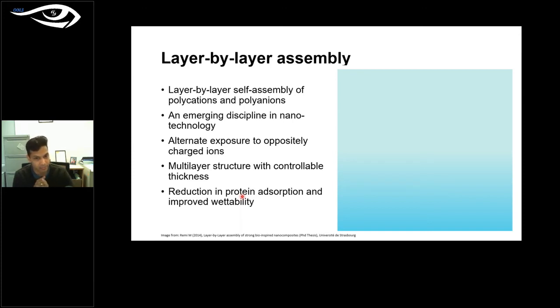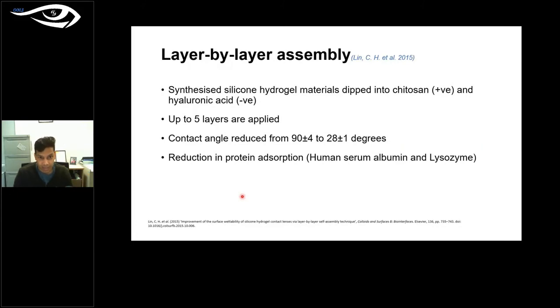But by making a lens more neutral, that kind of protein adsorption can be minimized, and at the same time we can also improve wettability of the lens surfaces. So that's the layer by layer technology. And this layer by layer assembly is actually applied for contact lens materials also, for example, silicone hydrogel lens materials. When it is applied onto silicone hydrogel lens materials, it is dipped into positively charged chitosan and negatively charged hyaluronic acid. In an experiment conducted by these researchers, they applied up to 5 layers, and with each layer of application, they noted that the contact angle was becoming better and better.